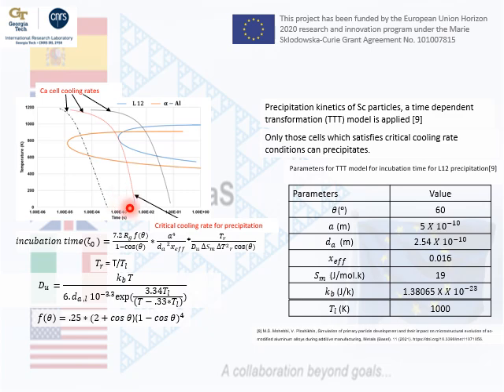However, this happens because at high temperature, during solidification, there is a region where we observe the formation of particles, the scandium aluminum second phase particles, right? And because suddenly in the liquid we have an additional phase at the surface between the particles and the liquid, we also have a reduced work of nucleation. So essentially this means that the probability of nucleation increases. And in any region where we observe a pronounced nucleation of particles, we are also going to observe a pronounced nucleation of crystals, right? So solidification is going to result in these fine grain structures, as we are going to see also in the future.